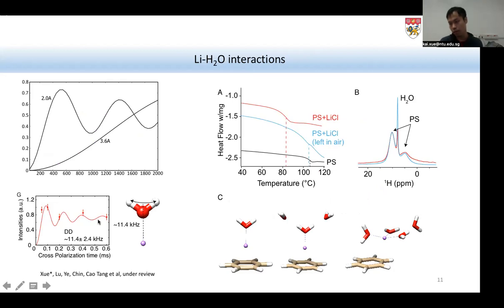The lithium to water binding mode has been studied for quite a long time, but since protons and lithium are quite light for X-ray, only in 2016 and 2017 did synchrotron give some structures which I think are more reliable for the binding mode. But we all know the problem with synchrotron: it is not as flexible as solid state NMR, because we are less picky about sample state. So in this work, I only want to verify one point from simulation.